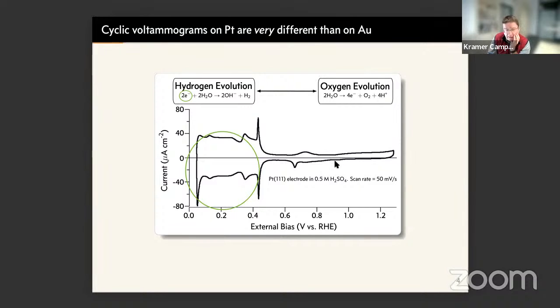And you can see quite clearly that this is much more complicated than the voltammogram on the slide before. Now, on the negative arm, there is a small current feature at around 0.65, 0.7 V versus RHE. This is thought to be a phase transition in the adsorbed sulfate. If you continue still more negatively, there is this characteristic butterfly feature. This is thought to reflect sulfate desorption and hydrogen adsorption. If you continue going still more negatively, scanning the bias towards zero, you see this abrupt negative current feature, and this is, of course, hydrogen evolution.